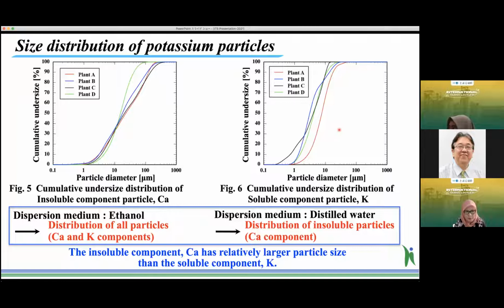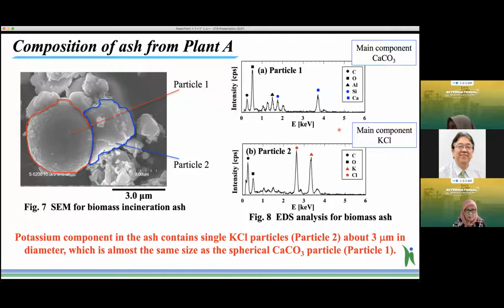So to investigate the form of the potassium component in the ash, SEM observation of the original ashes and their elemental analysis by EDS were conducted. The results are shown in these figures. These figures reveal that the potassium component in ash, this is particle 2, consists of KCl. So the potassium component in the ash exists as single KCl particles about 3 micrometers in diameter, which is almost the same size as a spherical CaCO3.